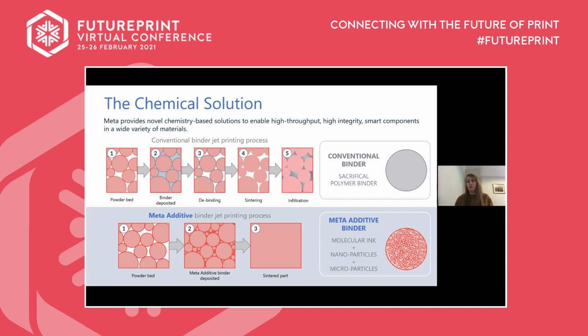So the actual printing process itself is quick, but this debind, the heat treatment step, the infiltration step is limiting the processes in which you see binder jet being used. So Meta came from a different angle, and we used a chemical approach, as I said at the beginning. And we can see that limits this down to 3 steps.